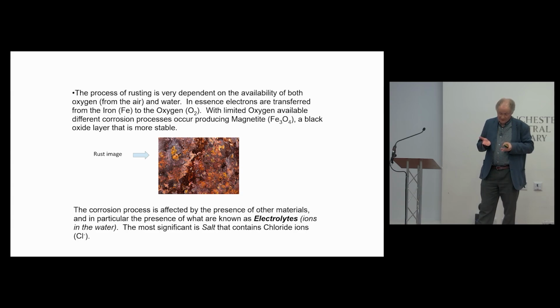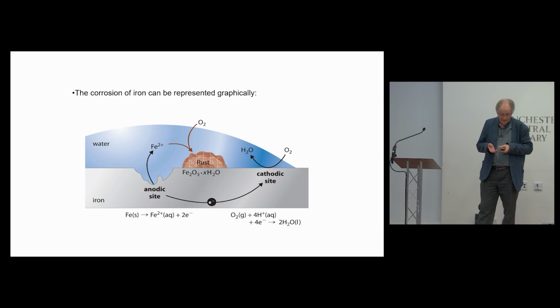And there is one particular scenario which causes iron to corrode much more significantly, and that's when you get salt present. So anything that's near a coast or buried in the ground, you get penetration of salt, and particularly chloride ions, into the surface of the metal, and that significantly increases the process of corrosion. Because if you can imagine, salt's hygroscopic, so it will draw moisture out of the air, and then the chloride ions go right down to the surface of the metal and are very difficult to remove. For those that like little chemical drawings, there we go. This is a diagrammatic version of what goes on.